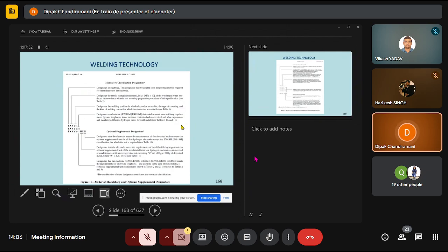And now we want to talk about the electrode designation, because when I have A516 Grade 70, I want a 70,000 tensile strength. When I have A516 Grade 60, I need a 60,000. I don't want to overmatch because I get no credit for it. If I'm welding A516 Grade 70 to Grade 60, I need only a 60 weld metal. That is what the code says. The lower of the two must be met. By making it stronger, I can put 80,000 weld metal also, but I get no benefit from it. So it's going to cost me money. Why should I do that?